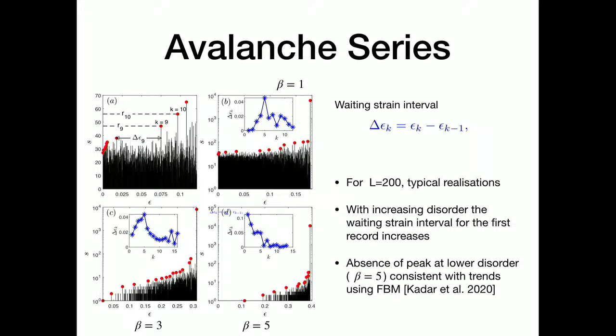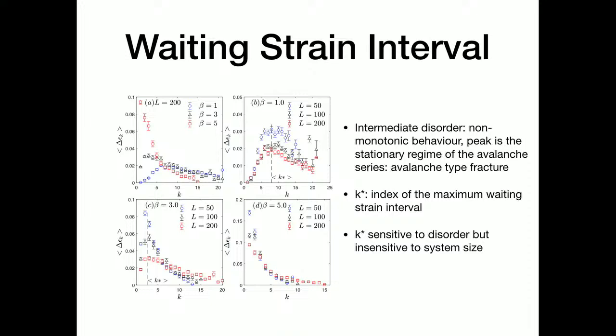So this is a single realization of each of these disorders. If we look at the averaged behavior, this is for system size of 200. We are changing the disorder. For the intermediate disorder that we have, I want to call it high disorder, but since high disorder is beta equal to 0.1, intermediate disorder here is, you see that there is a formation of the peak that we were talking about, these blue markers, and as you lower the disorder by increasing beta, that peak shifts from here to there, and then you have only acceleration type of behavior.